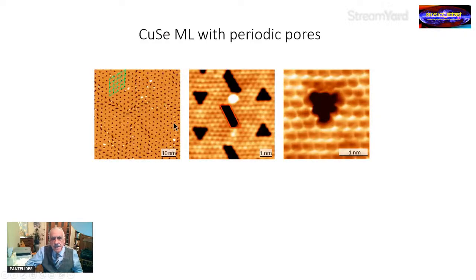We tried copper, and we got a very different pattern. In the monolayer copper selenide, we had little holes of triangles, either in this orientation or in this orientation, with this kind of boundary that you can see here. Here is a close-up image of one triangle. And in this case, we succeeded.